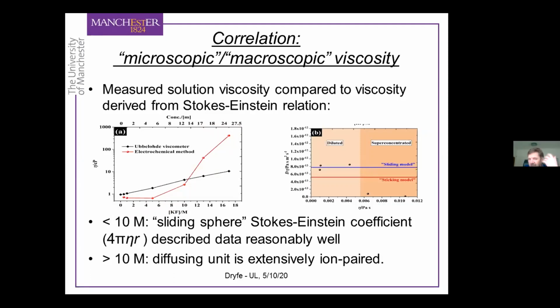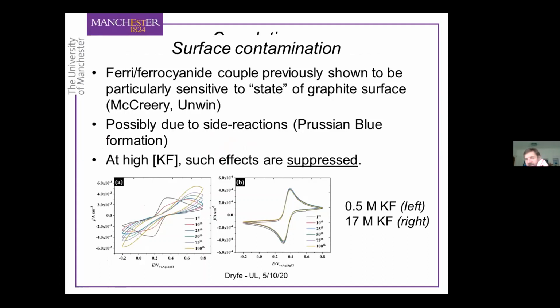But I think these effects are still very interesting, and I'm really surprised at how little literature there is, that I've been able to find at least, on just really basic electrochemical experiments on these highly concentrated aqueous electrolyte solutions. And again, just to come back to the surface contamination, as I've said before, if you measure ferricyanide on basal plane graphite, the first CV might look okay, but rapidly it looks horrible. The first CV doesn't look that great, but after a while of repeated cycling, you get something that looks distinctly weird at normal electrolyte concentrations.